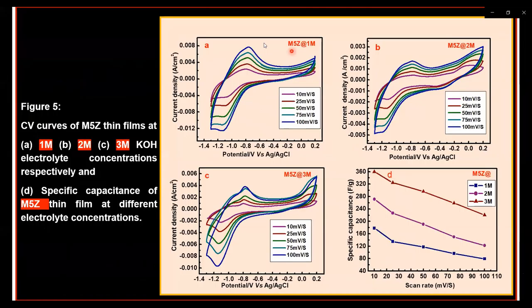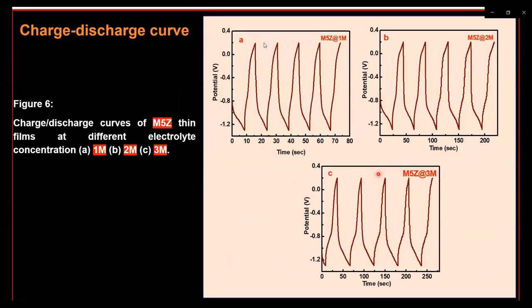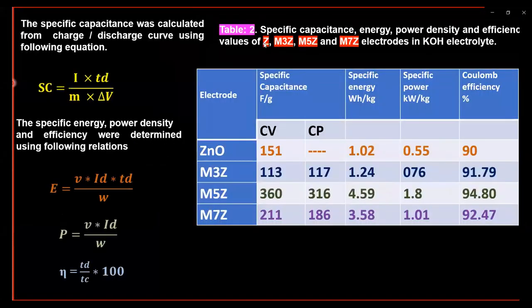This next figure shows 5% Mn tested in 1 molar, 2 molar, and 3 molar. And it shows specific capacitance, 3 molar shows the specific capacitance 360 farad per gram. Next is charge-discharge curves. This charge-discharge curve shows symmetrical shape. It is for only 5% Mn in 1 molar, 2 molar, and 3 molar. All these curves show a similar shape.